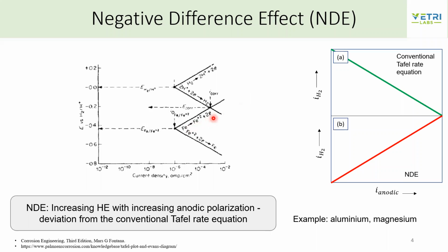For instance, if we drop iron in an acid, iron is going to dissolve and form Fe2+ and 2 electrons. Whereas when we drop a passive metal which has a passive film on its surface, such as aluminium, it's not the aluminium that's dissolving directly—well, of course it is—but the surface immediately in contact with the electrolyte is nothing but aluminium oxide, the passive film.